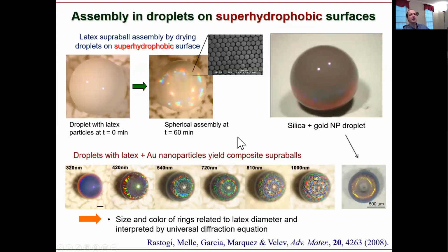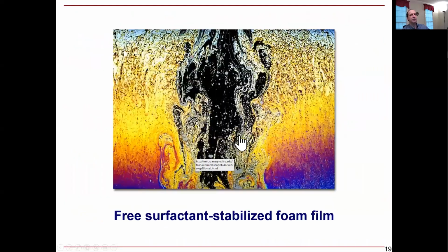Okay, so just a few more examples here. What I'll discuss next, and I'm not going to go through all the formulas, but you can have those slides, and we can have the recording. Something that I have been doing as a graduate student when investigating foam and emulsion films is correlating the color of the film. In reality, you don't use color light, but monochromatic light of a certain wavelength, and you just measure the intensity. If you use polychromatic light, which is the usual white light, then you're going to see beautiful colors because you're going to have interference and diffraction in thin film at different conditions as the film thins, right?